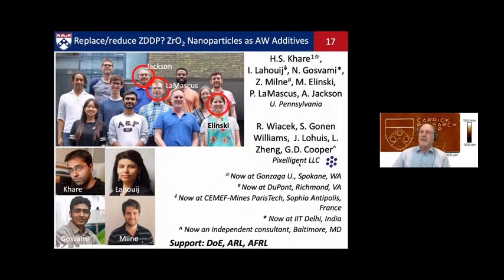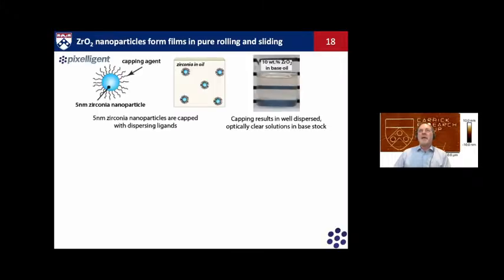And this is a collaboration with Pixelligent, a company based in Baltimore that makes nanoparticles. So they formulate these very monodispersed zirconia nanoparticles with an organic capping agent that allows them to be highly soluble in oils, including base oils or even fully formulated gear oils. They're very well dispersed. They're stable for months, actually years in solution.